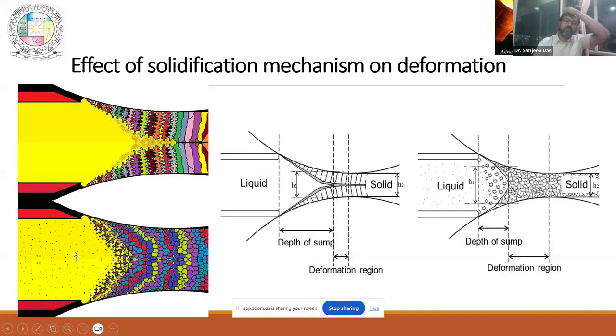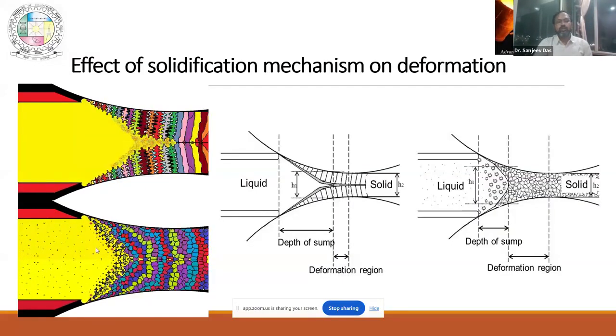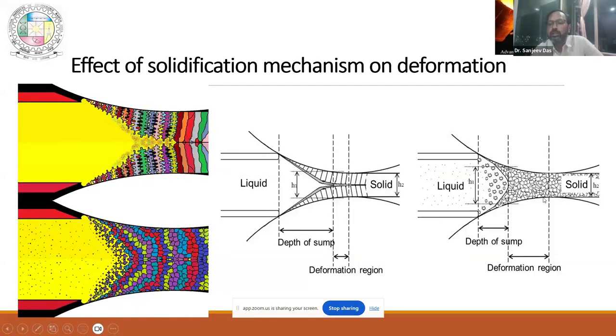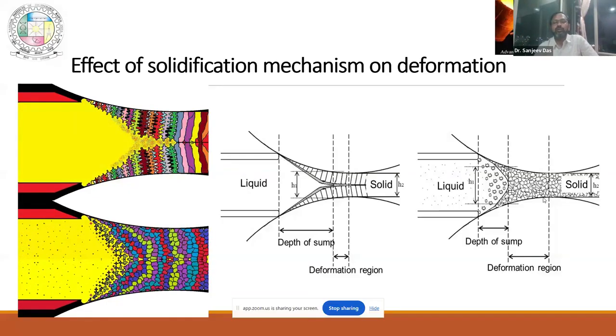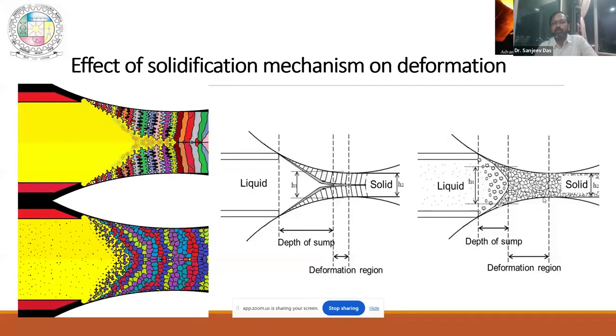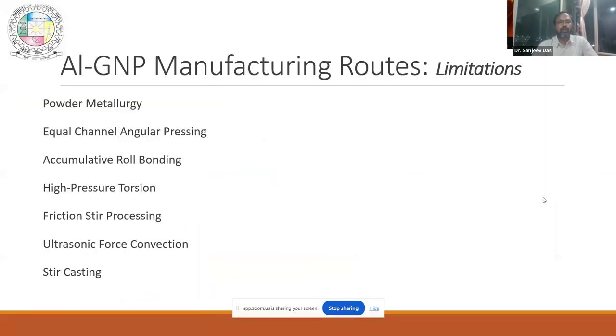But if you have some convection, if you are adding any particle, or if there is any alloy, the nucleation starts in the liquid, not from the surface to the interior. And your deformation region increases. And when the deformation region increases, you create a lot of defects like dislocations, which help in recrystallization, dynamic recrystallization. So it is very easy when you have more deformation, and that's why less time is required when you are heat treating the material and getting the structure. Okay, now let us come.